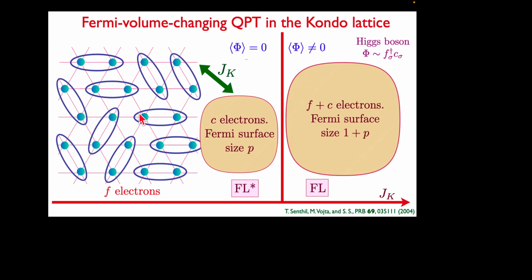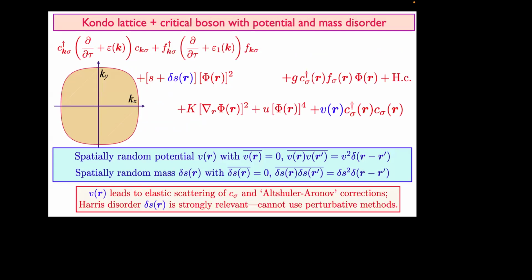Okay, so if you want to look at the theory of this transition, you can write down some field theory where you have the spinons and the electrons, and they couple to this Higgs boson, which converts a spinon to an electron, and you write down some Landau-Ginzburg action for the rest of the fluctuation. This is the canonical Hertz-Millis procedure. But now you put in some disorder. The usual way you put in disorder is in elastic scattering of the electrons, and those effects are relatively weak. It turns out the most important effect is a fluctuation in the local position of the critical point.